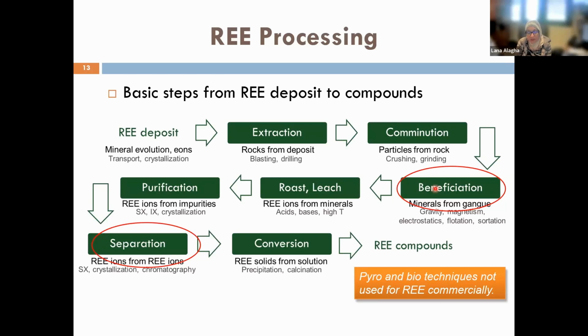This includes gravity separation, where the separation depends on the difference in density between the various minerals, or magnetic separation, where the separation principle focuses on the difference in magnetic susceptibility. And we know that a lot of rare earth minerals are paramagnetic, so they can be concentrated using a high intensity magnetic field. Then electrostatic separation, which utilizes the difference in polarity or conductivity between the minerals. And then flotation, the most selective and famous type of physical separation process, used extensively in the separation of rare earth. It is a physical separation method, not a chemical separation method, although we are adding many chemicals in the flotation to enhance the selectivity of the process.